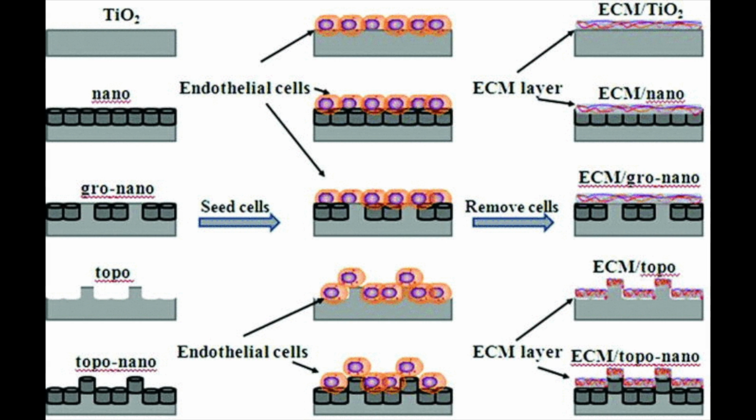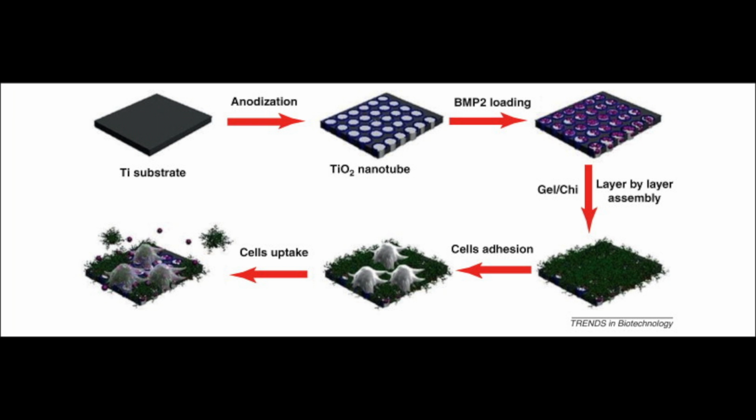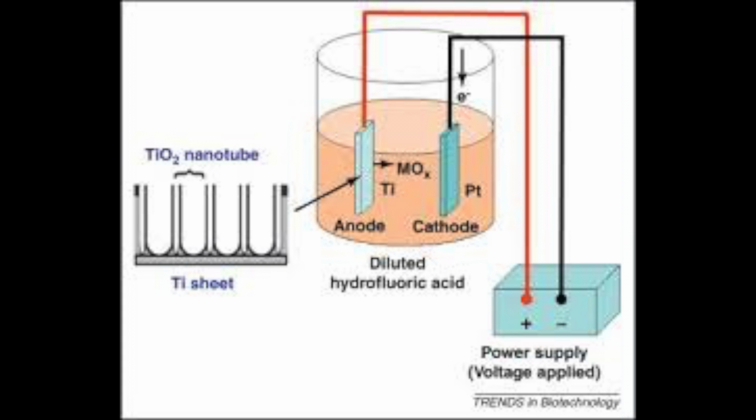Well, Stevie, there are many different materials that could be used to help guide the path for your differentiation. One possibility is titanium dioxide nanotubes, which can influence you into becoming a contractile smooth muscle cell. Nanotubes are tubes that have their diameters in the nanoscale range. Titanium dioxide is non-toxic, which makes it great for biomedical applications. The nanotubes create a high surface area, which allows them to be more effective. The high surface area and unique nanogeometry allow for greater control of the chemical and physical properties of the titanium dioxide. The tubes are made through an electrochemical oxidation process applied to titanium substrates.